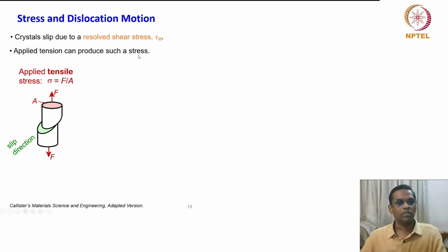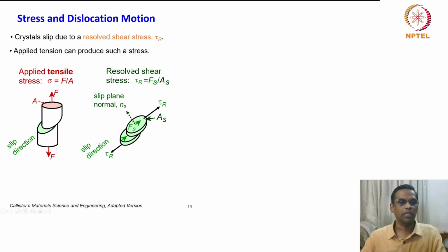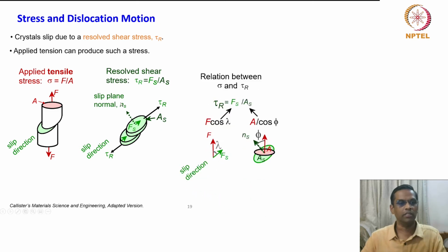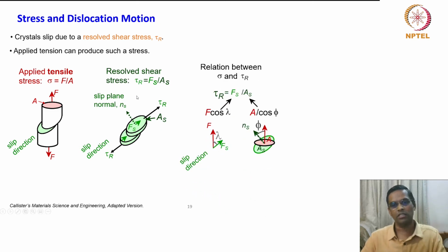So applied tension can produce such a stress, and the resolved shear stress, tau R, is equal to the shear force divided by the area where the shear force is acting, which will give the resolved shear stress. And if you look at this schematic, it clearly depicts the area which is subjected to the shear force as well as the plane on which the shear force is acting. And then you see this NS is a slip plane normal, just to give the illustration clearly between this applied tensile stress versus resolved shear stress.